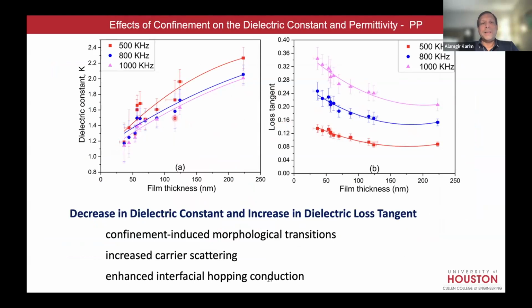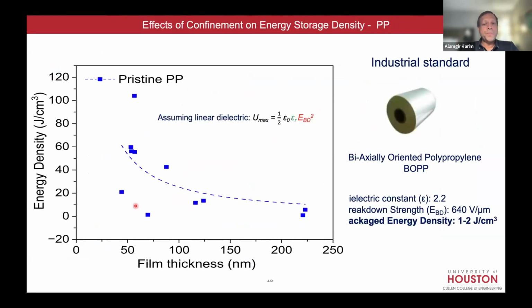So you may think at this point that, well, if I lose 30% dielectric constant in the permittivity part, then the breakdown goes up. Maybe they kind of cancel each other. There's no net energy enhancement. That's not true, because the voltage enhancement was much larger than this 30% drop of dielectric constant. And so here, if you calculate the product of the linearly increasing or decreasing permittivity with thickness, but the very sharply increasing breakdown strength, you still come out winning. You can see that 250 nanometer, your energy storage might be like 5 or 6. That's consistent with BOPP as we know it.